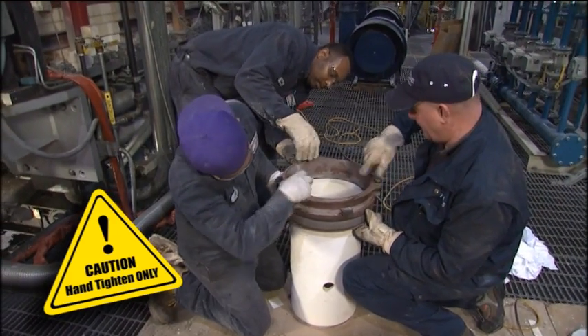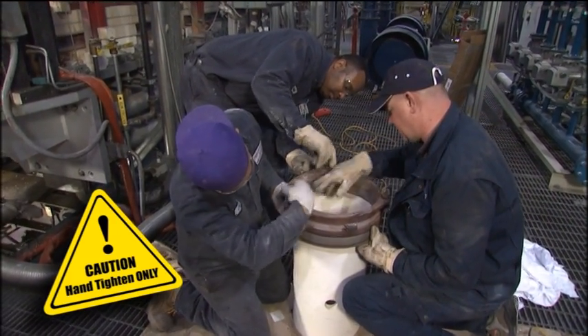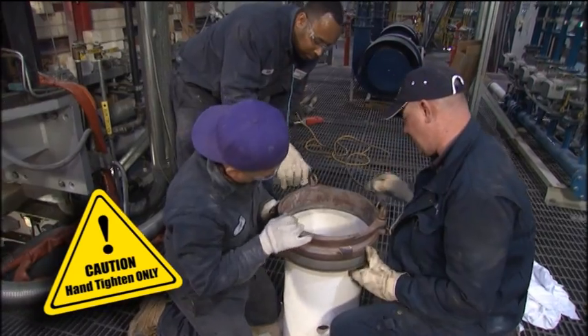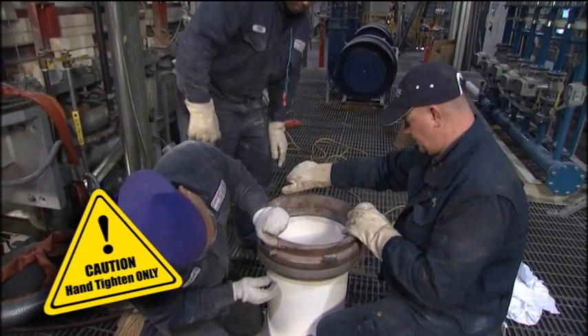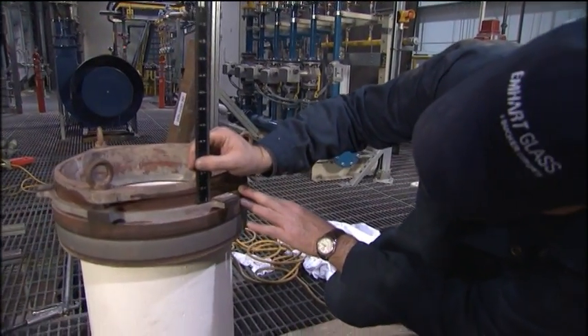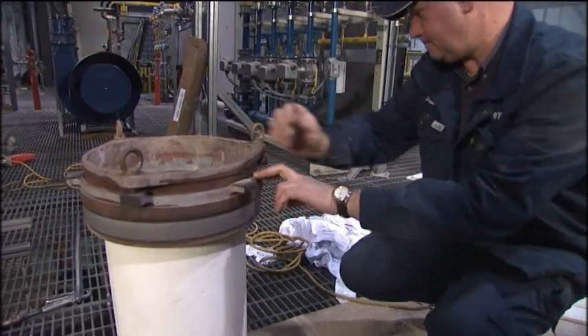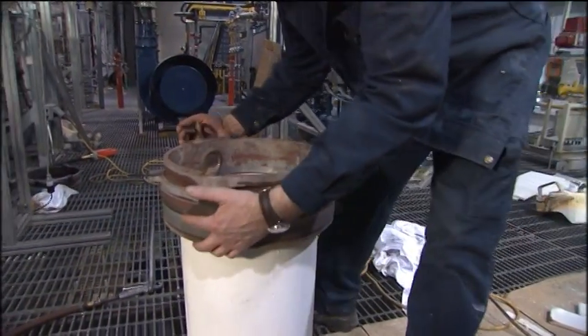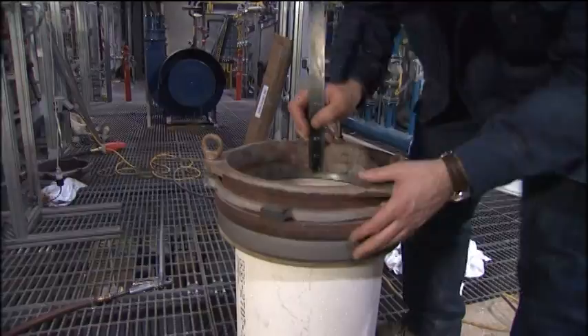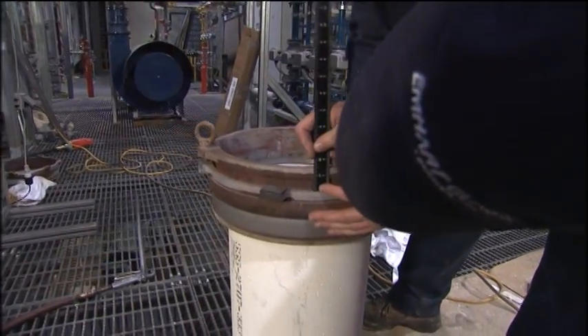If these bolts are over-tightened while the tube is cold, it can cause the tube to crack and break around the flange area upon heating. Over-tightening at this stage can also lead to stress cracks which may not present themselves until later in service, be it days, weeks, or months.